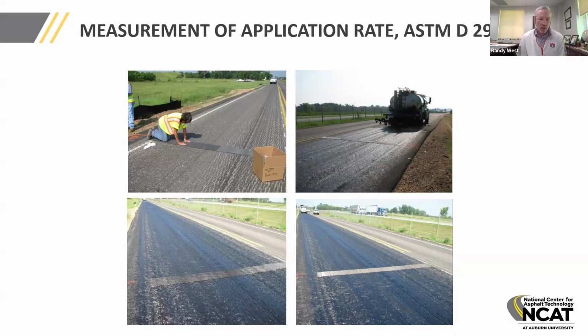In the case of emulsions, you've got water and the residual asphalt. So you've got to let those pads dry out, put them in a temperature controlled oven to dry them out to a constant mass. And then you have the residual rate. And that's really important because the other methods of measuring tack coat application can fool you. One of the ways that a lot of people do it is they'll just ask the tack coat distributor driver what the computer says on the distributor computer. Those computers are notoriously inaccurate. In fact, in my work, I've yet to find one that gave the actual application rate that we were shooting for in an experiment.